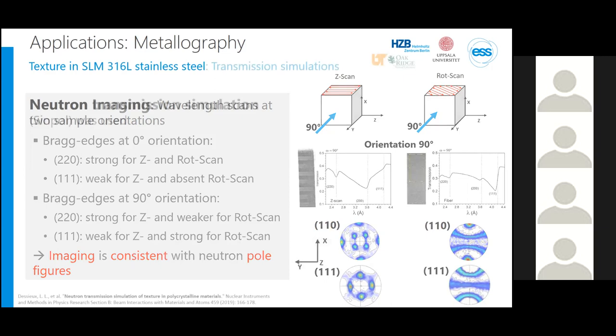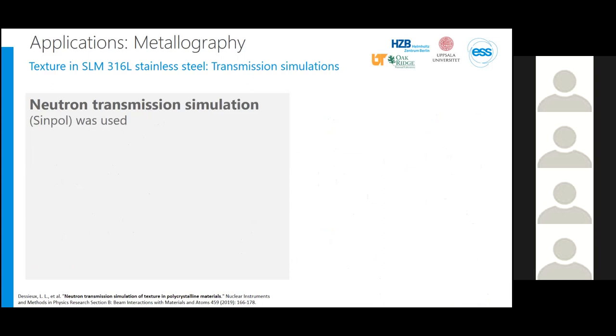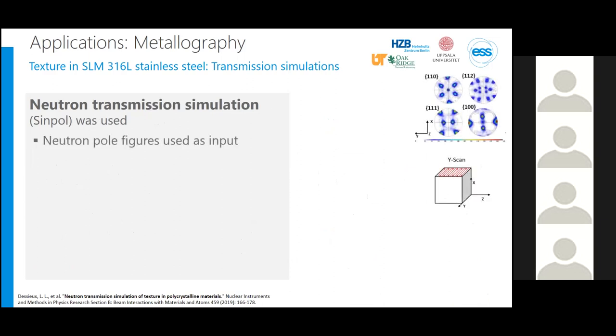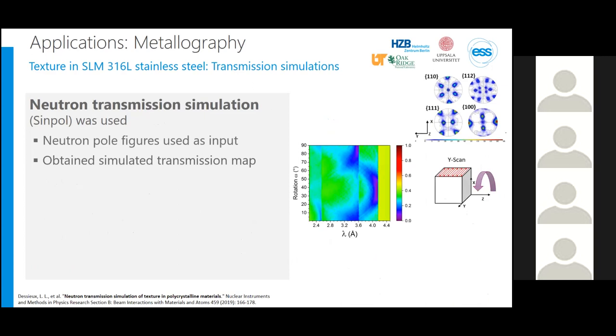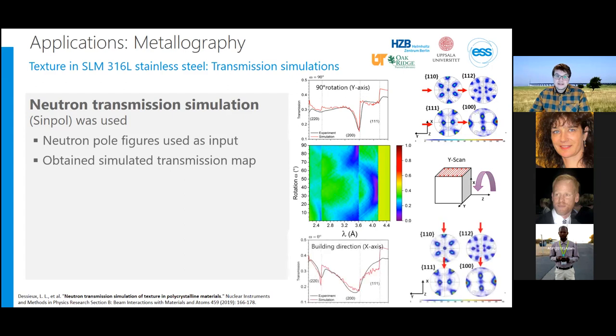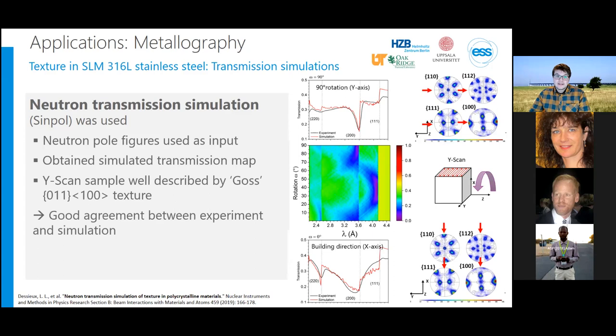Moreover, in this particular study, through a collaboration with colleagues in Tennessee, we obtained simulated transmission maps. We used the neutron pole figures as input parameters, from which we obtained the transmission intensity, in this color scheme between purple and red. Red means the transmission is one, so there's basically no sample in the beam. This is shown as a function of wavelength on the x-axis and sample rotation on the y-axis. Here you can see it overlaid with our experimental data when the sample is at 90 degrees, and on the bottom at 0 degrees. Again, we see a very good agreement between our experiment and the simulation, and we have simulated it for many more rotation angles than we were able to measure.